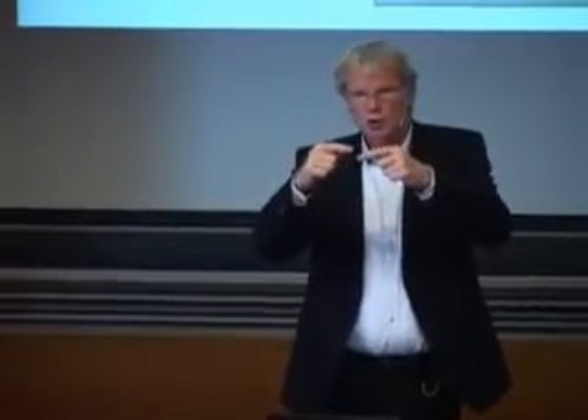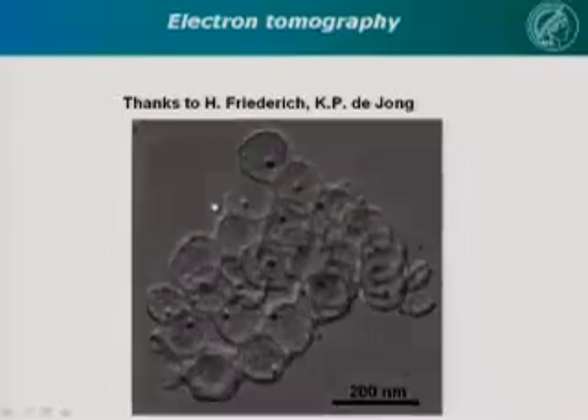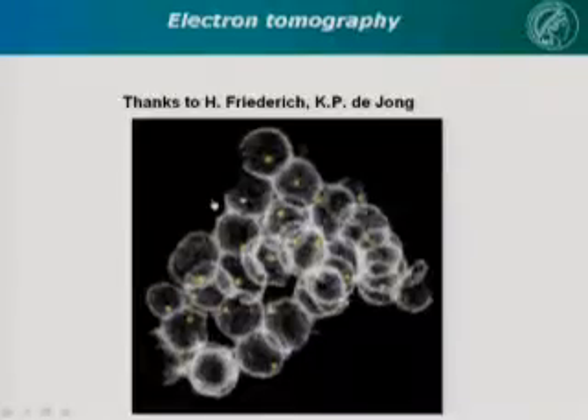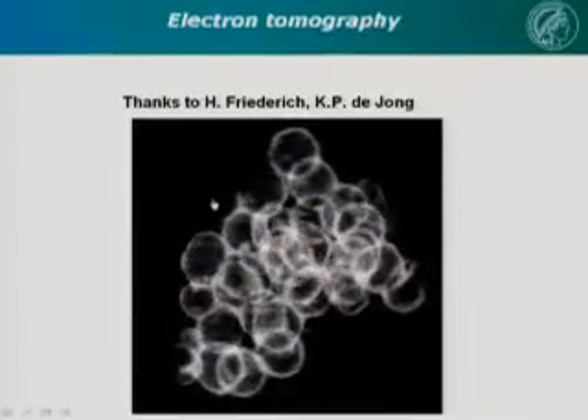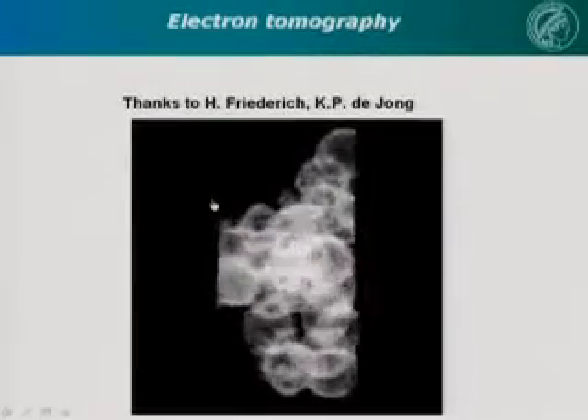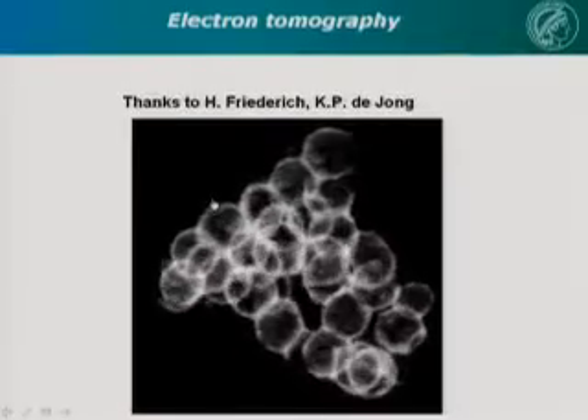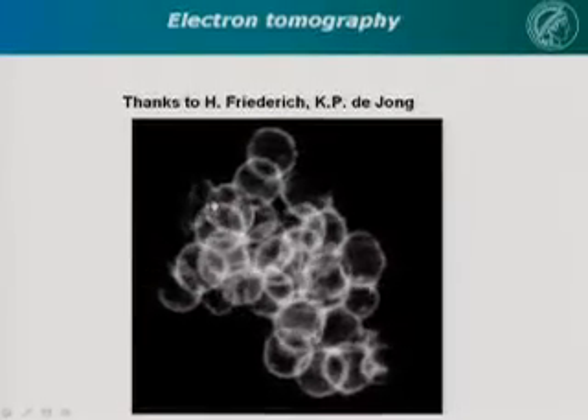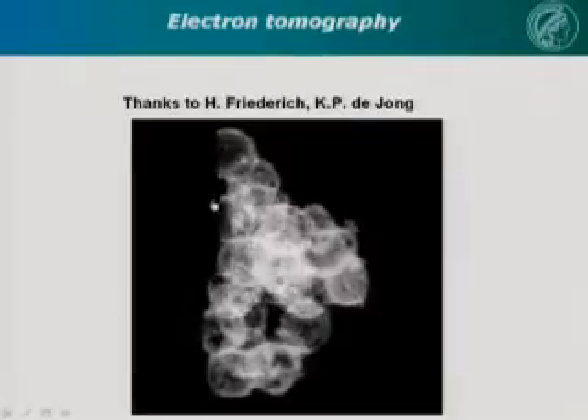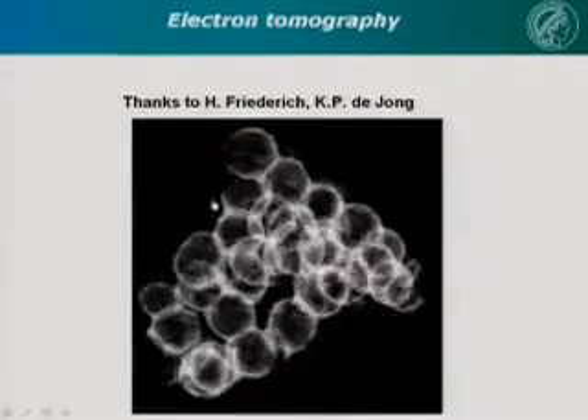And then in a computer, they reconstruct it to a 3-dimensional representation of the sample. And this is what you now see. And then you can also play tricks on the computer. You can actually highlight the gold particles and the shells, and you take them out for the analysis. So here you see, this is artificially the gold particles taken out by image processing. But you can see these shells are intact.